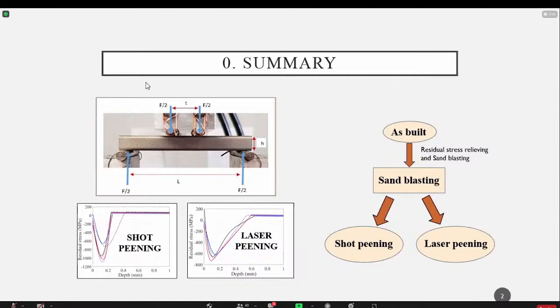So the main goal of the present work is to understand how the cracks emanate and evolve from an internal defect in a fatigue test of this titanium alloy made by selective laser melting. We measured, of course, the residual stresses that you can see in the figures down in the slide, and we tested the specimens in 4-point bending, which I think is an important fact. We can later discuss it in the questions if you want, because this tries to avoid some problems.